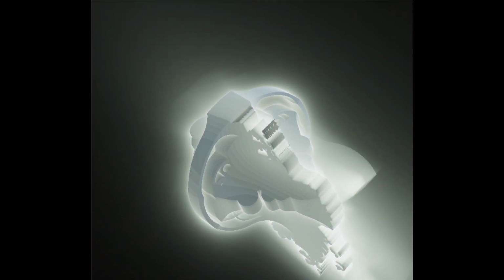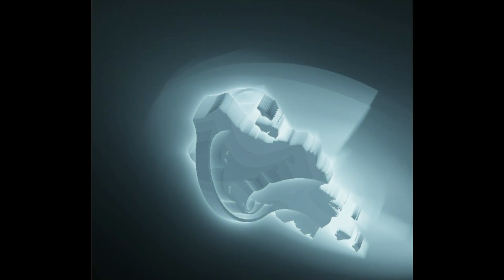Graphene has better dielectric screening, which weakens long-range interactions, and it has weak spin-orbit coupling. This favors the short-range physics of the Mott state. Okay. TMDs, on the other hand, have poor screening, so long-range Coulomb forces remain strong. Plus, they have strong spin-orbit coupling. These factors favor the electrons ordering themselves into a Wigner crystal to minimize that long-range repulsion. So the Moiré platform lets you choose your material to emphasize different fundamental interactions. That's powerful. So it's a key design principle.